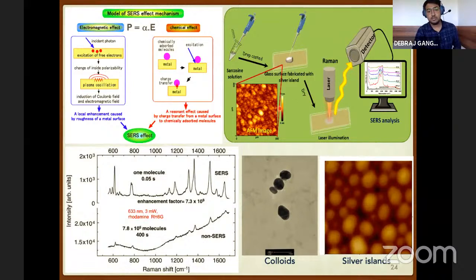This is how we record the SERS spectra. We have our substrate, and we put a drop of the ANALYTE solution, and then we can directly put it under the Raman microscope, and we record the Raman scattered signal through a detector, and we get SERS spectra in this way.